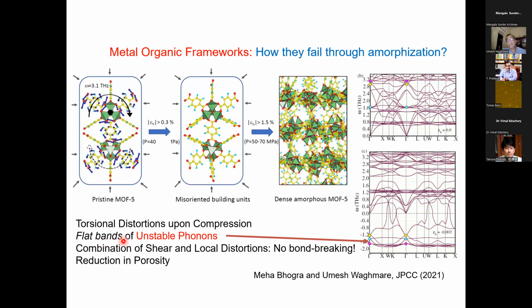Flat bands is another emerging idea in the physics of condensed matter. What it means is, since the eigenvalues of all these modes are roughly the same, any linear combination of those modes are also eigenvectors of the system, vibrational eigenmodes. So you can basically have highly localized distortions in the crystal, and they can be random. So these flat unstable modes allow this crystal to deform in a random way in different local regions, and that gives rise to amorphous phase. Basically, that's what we showed in this paper published just last year in JPCC.